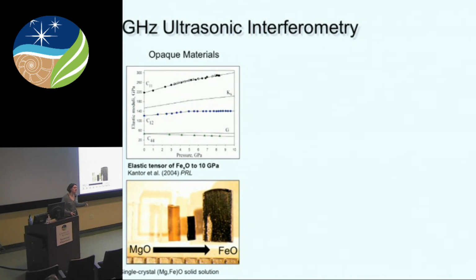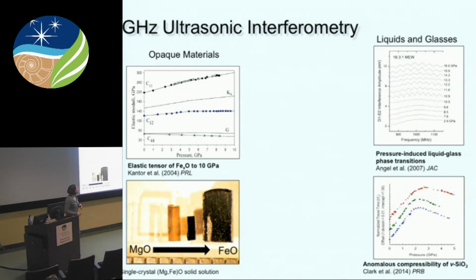And just because this is such a unique instrument, it's the only one in the world that does gigahertz ultrasonic interferometry, I want to tell you a few of the capabilities that are unique to it. One thing is that it can measure velocity in opaque materials, and this is problematic in other velocity measurement techniques like Brillouin spectroscopy, where you're using lasers, because lasers would couple with an opaque material. It's also particularly well suited for velocity measurements in liquids and glasses. This is some of my work down here on silica, and this is looking at methanol-ethanol-water going through the glass transition from where it doesn't support a shear wave to where you have a well-established shear wave.